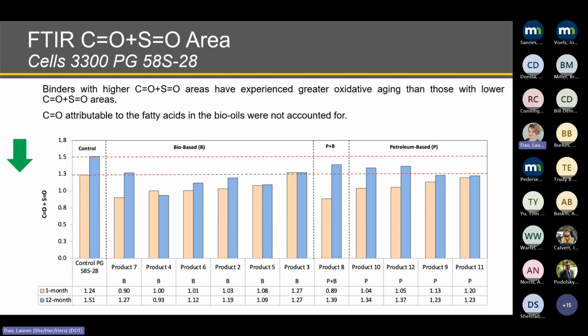The other chemical evaluation performed for this study was FTIR to evaluate the carbonyl and sulfoxide areas, because it's known that if a binder experiences aging, that binder would have a higher area of carbonyl plus sulfoxides compared to a binder that was less aged. It is known that these products, especially the bio-based ones, have fatty acids that contain carbonyl groups that, if not corrected, could indicate these products as being ineffective in terms of oxidative products when considering FTIR evaluation. Therefore, what was done here, we use an approach where only the carbonyls that are attributed to the binder were considered in the calculation. So the fatty acid carbonyls were not accounted for in this.